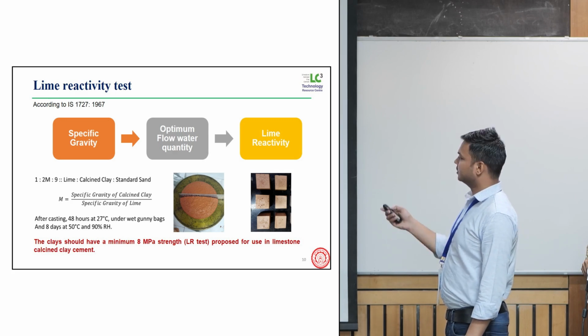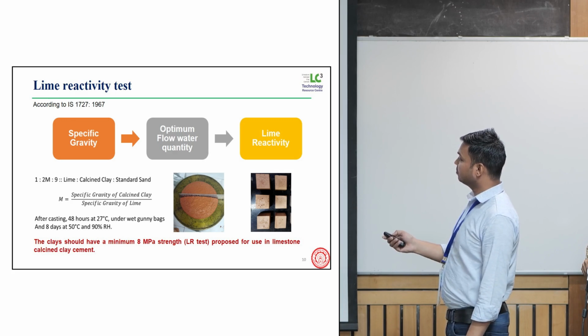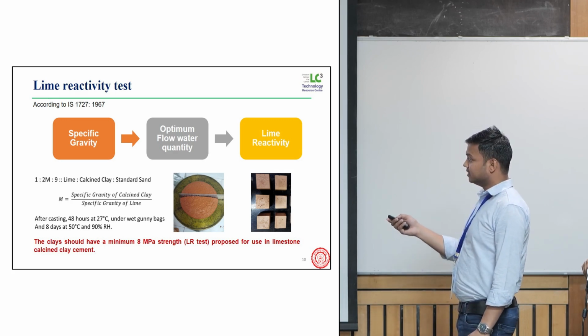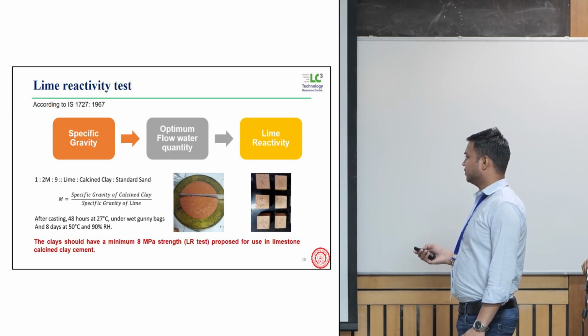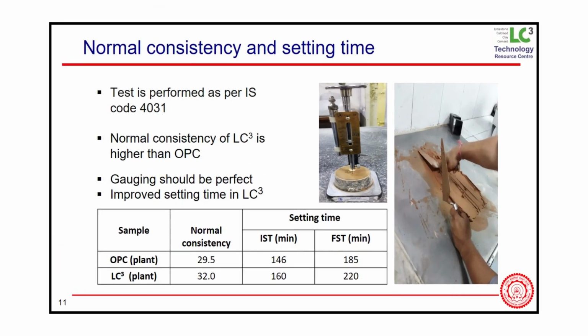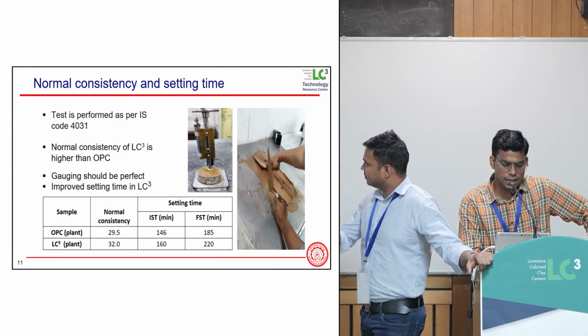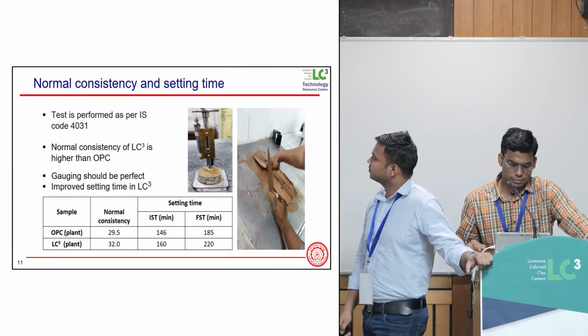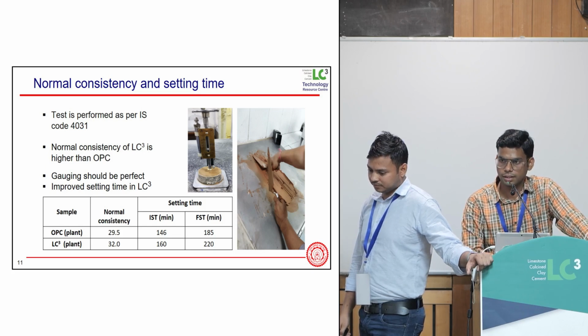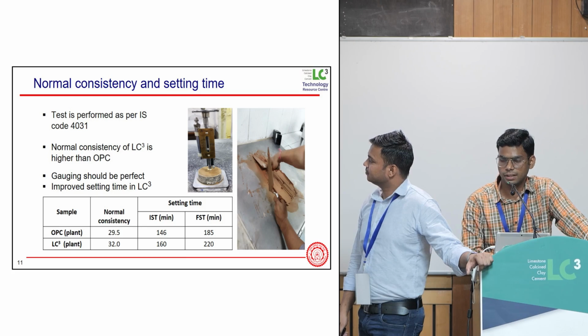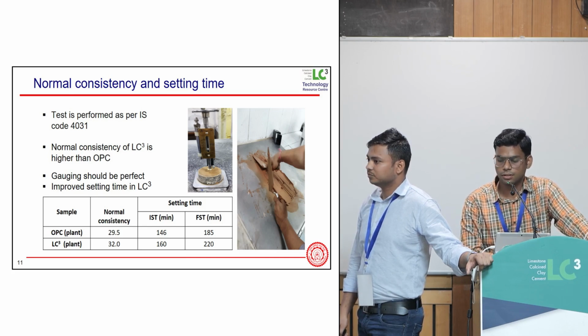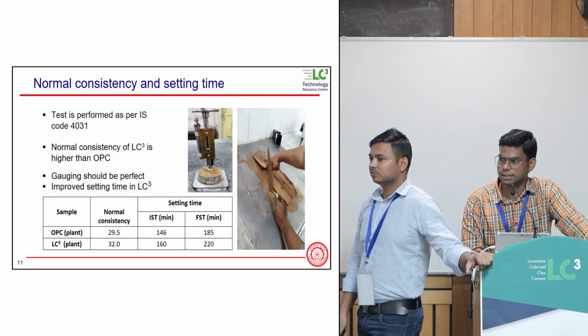After 8 days of curing at a certain temperature and humidity, we get the strength. The strength should not be less than 8 megapascal, as proposed for limestone calcined clay. Normal consistency and setting time are important parameters for our LC3, and normal consistency is performed according to the Indian Standard Code 4031. Generally, the normal consistency of LC3 is higher compared to OPC. We have also learned that the grinding of the material is important for normal consistency. If the LC3 is finely ground, we get 2 to 3% higher NC compared to OPC. But if the LC3 is not properly ground, we may get a 4 to 5% increase in the NC of LC3 compared to OPC.